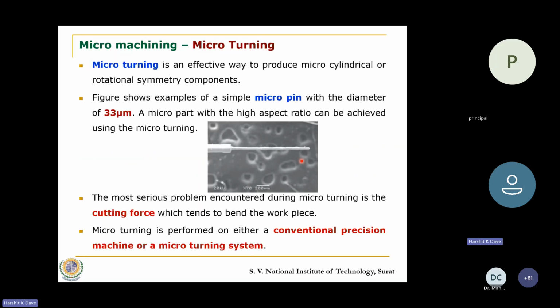To begin with, micro turning. Micro turning is an effective way where we produce micro cylindrical or rotational surface. If you can see this, this is a micro pin, and this micro pin would be around 1 mm, from here to here. But because this is put under a microscope, it appears to be very large. But this is the dimensional scale of 200 microns. So roughly this would be somewhere around 1 mm. And its diameter, which was measured, was 33 microns.